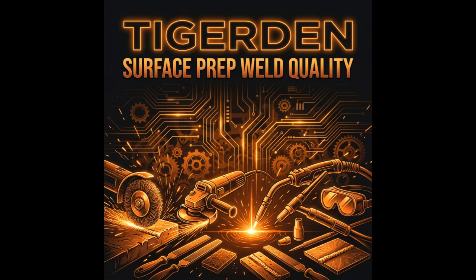It's that dark bluish-gray coating on hot-rolled steel. It looks like it's part of the metal, but it's actually a brittle layer of iron oxide. If you weld over it, the arc has to fight through that scale to get to the actual meat of the steel. It makes the arc jumpy, and it prevents the weld from actually fusing into the base material. You'll get a weld that looks okay on top, but is basically just sitting there like a scab, ready to pop off the first time someone bumps it.